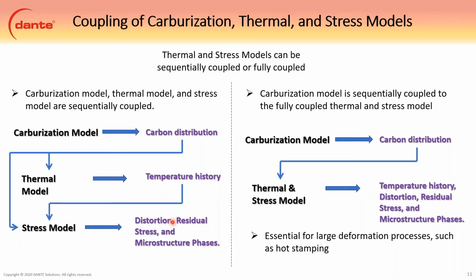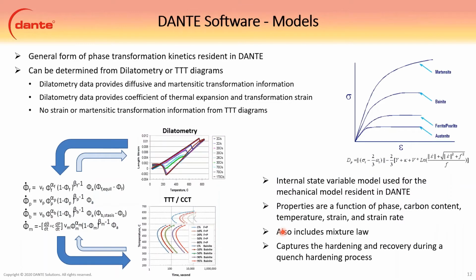If the distortions are larger, like for hot stamping, then you can couple the thermal and stress, but it generally takes a little bit longer to run, but the accuracy is better. And if you have large deformations, it's necessary because the thermal properties can change a lot quicker.